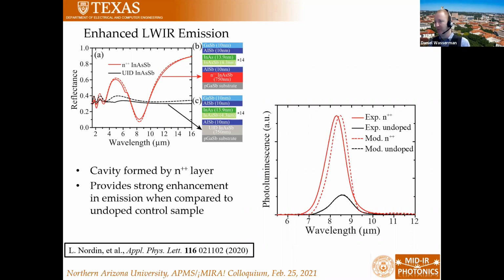That scattering term in the Drude model is a loss term, and that's going to kill you every time. So there is absolutely a limit. It's not as if we can make a Q of 2 million type cavity with the plasmonic material just because it's an epitaxial material. Our Qs for any sort of resonant structure in the mid-IR using a plasmonic material, I think we'd be lucky to get to 200, 300. I think that sort of level would be reasonable.